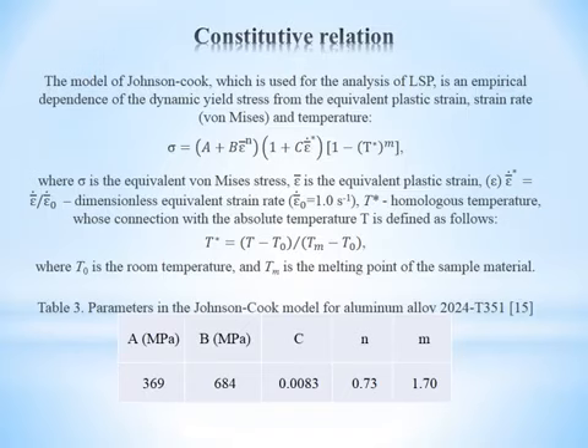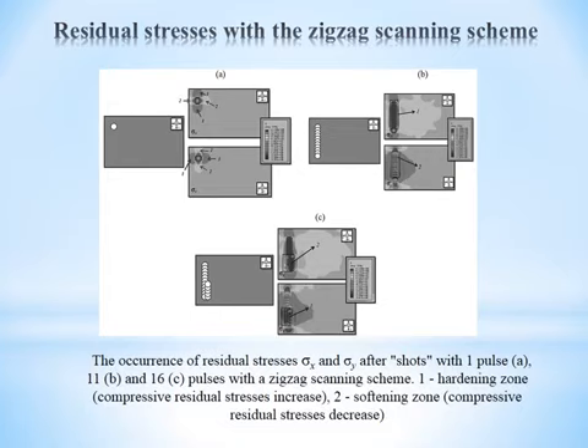In our work, the Johnson-Cook models will be used. Before analysis of the situation with respect to the residual stress arising from multiple laser pulses, it is necessary to study in detail the features of the appearance of residual stresses sigma x and sigma y after a shot by a single laser pulse. The result of the simulation is shown in figure A.